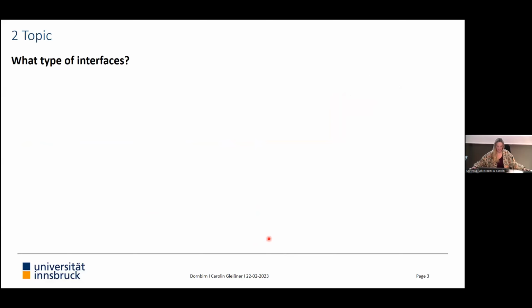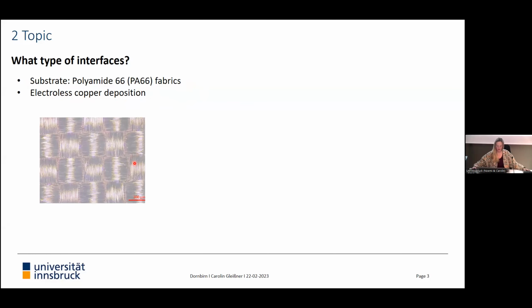So next question is, what type of interfaces? In my work, what I was looking at was a polyamide 6,6 fabric. And like Noemi already said, at the Institute, we investigated this technique of the electroless copper deposition. So that's why I also tested this technique on my fabrics. Here you can see a laser scanning microscope picture of a copper coated PA66 fabric, I think under magnification of 10.